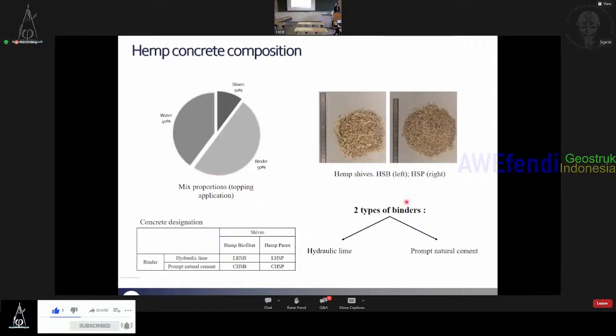Two types of shives have been used, and also two types of binders. Regarding the shives, the difference is mainly in the size. As you can see in here, those on the left side are quite bigger than those on the right side. Regarding the binder, we used both cement and hydraulic lime, which is the most used binder with this type of vegetal aggregates. It matches very well with the hemp or flax shives and gives pretty interesting mechanical performance.